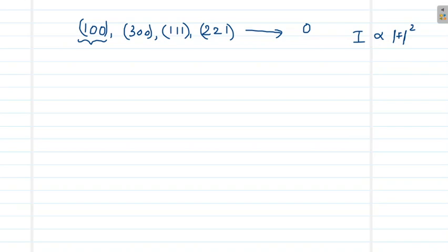But if you consider other sets of planes within this BCC lattice, such as the 200 plane or 110 plane, for all these planes the structure factor is 2f, which is the maximum value. So for these planes you will have maximum intensity. So what happens when h plus k plus l is odd? Even when all those planes exist in the crystal, we will not get a diffraction beam corresponding to those planes.